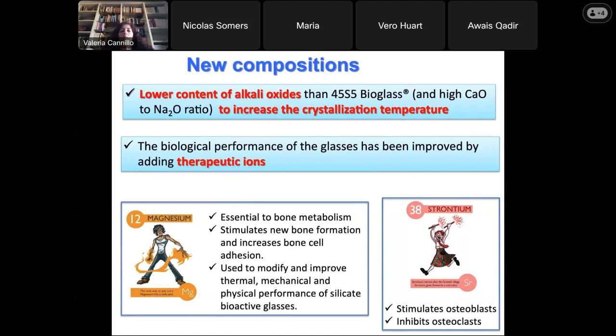So, there is a high ratio of calcium oxide to sodium oxide. And then the biological performance, as I mentioned, is improved by adding therapeutic ions, in particular magnesium and strontium. Magnesium is essential to bone metabolism because it stimulates new bone formation and increases bone cell adhesion. In addition, it is used to modify and improve the thermal, mechanical, and physical properties of silicate glasses. On the other hand, strontium is able to stimulate osteoblasts, and at the same time, it inhibits osteoclasts.